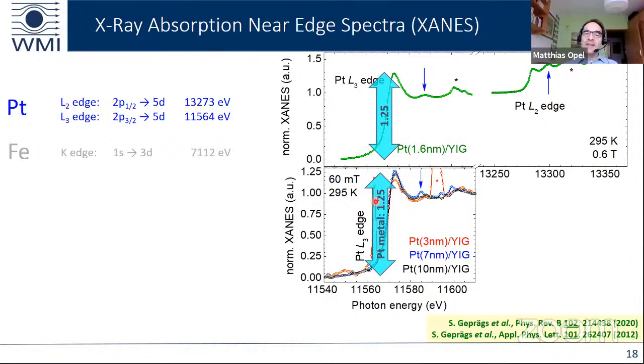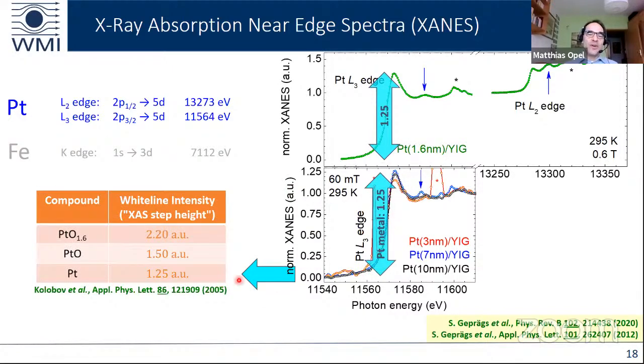Then we analyzed the height of this, so the step height of the X-ray absorption, the so-called white line intensity, in arbitrary normalized units, and we found a value of 1.25. And these 1.25 point to the existence of metallic platinum. I took this table from a publication by Kolobov, and they showed that metallic platinum has the lowest edge height, whereas platinum oxide or even higher oxidized platinum shows a larger white line intensity. So our results are compatible with metallic platinum.